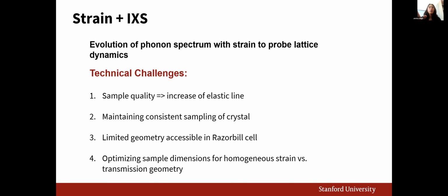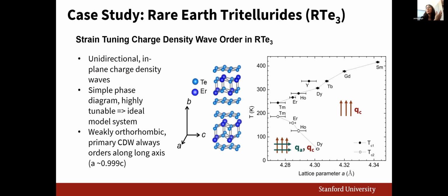All right, so the example material I'm talking about today are the rare earth tritellurides, and specifically I'm going to be talking about how we can use uniaxial strain tuning to manipulate the charge density wave order in these materials. So the rare earth tritellurides exhibit unidirectional in-plane charge density waves. And just a quick note on nomenclature here. For us, the in-plane axes are actually going to be labeled as the A and the C axes. Now, overall, this material family has a relatively simple phase diagram. Specifically, we're going to be focusing in our measurements on erbium telluride.